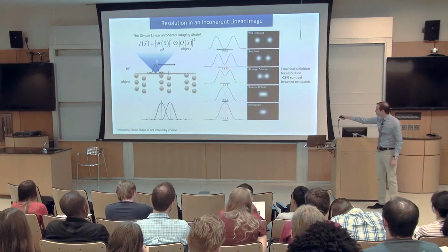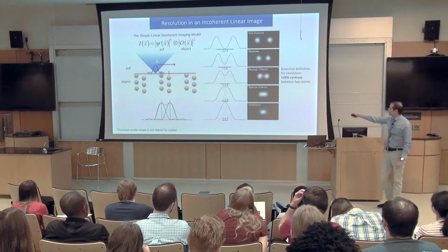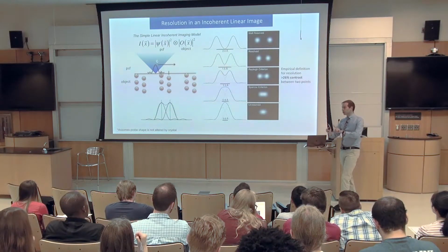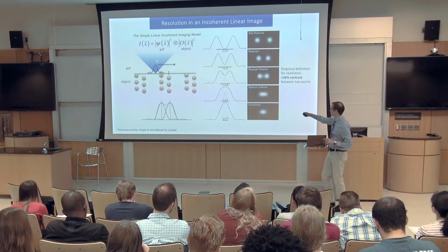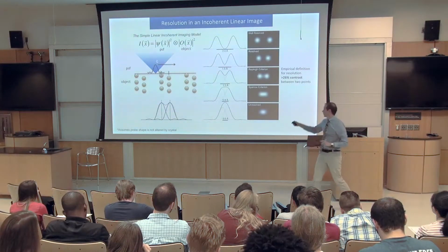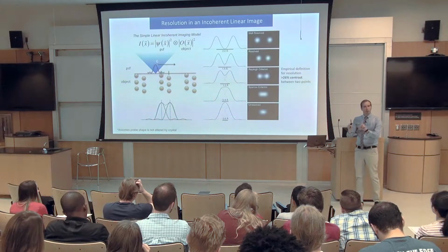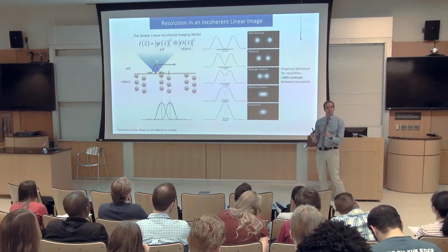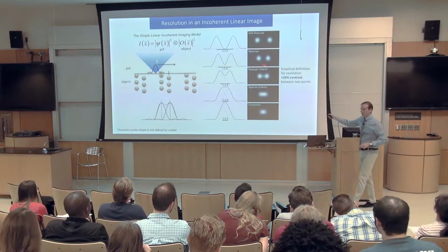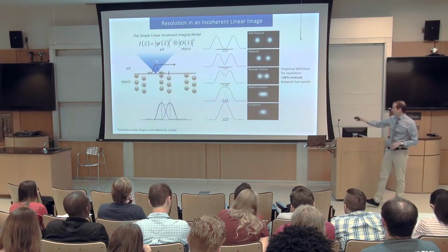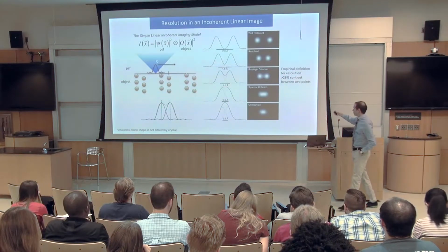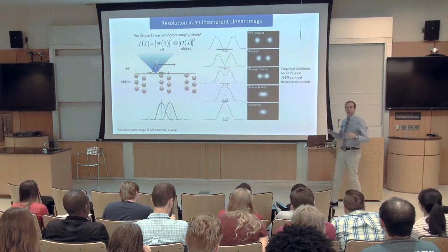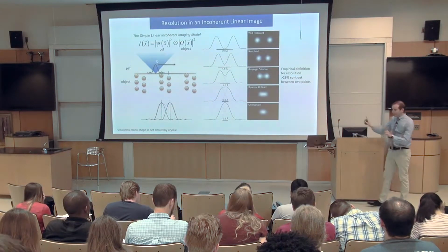It will rise to a point that is defined as the Rayleigh criterion, and that's a critical point where if the atoms get any closer, or the resolution, rather I should say, if the resolution gets any worse, then the peaks will move inward, and the position of these peaks will no longer represent the actual positions of the atoms. So the Rayleigh criterion is a good criterion for defining resolution. In practice, we just say if you have 26% contrast in this central dip relative to the 2 peaks, it's resolved.